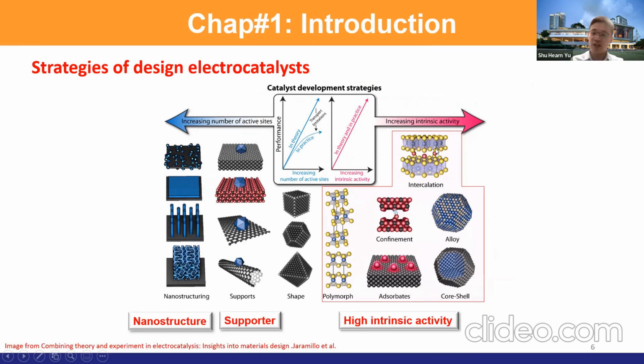For example, you can intercalate lithium ions into the MoS2 structure. As you increase the amount of lithium ion, the 2H structure of MoS2 will start to become 1T prime MoS2 and so on, because the layers can slide over each other as we increase the lithium amount. Also, we have something called alloying. If you put more chemical into the material, it's called alloying. If the amount is small, then we say it's doping.